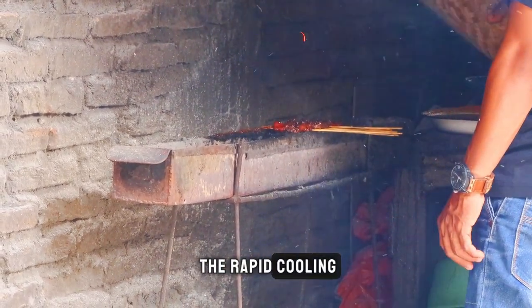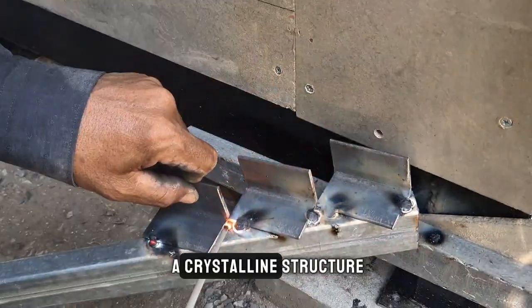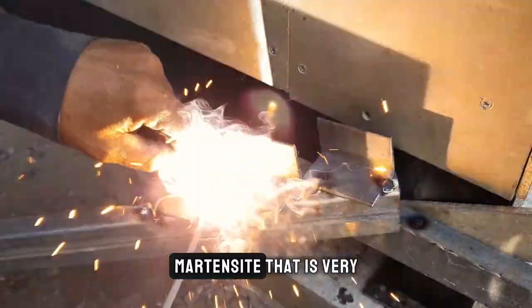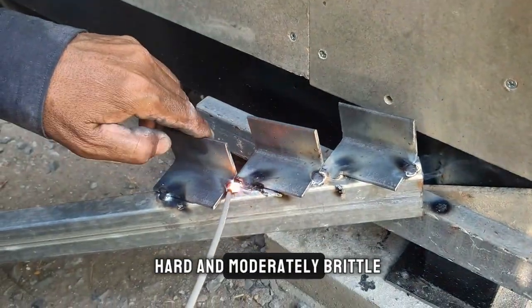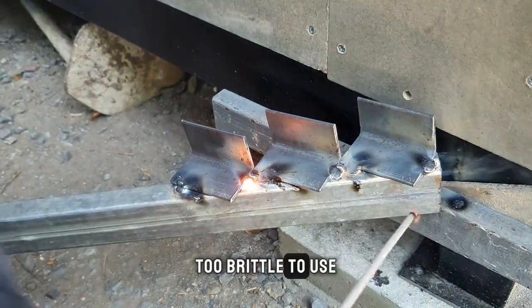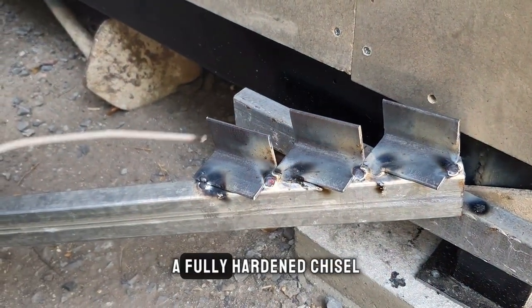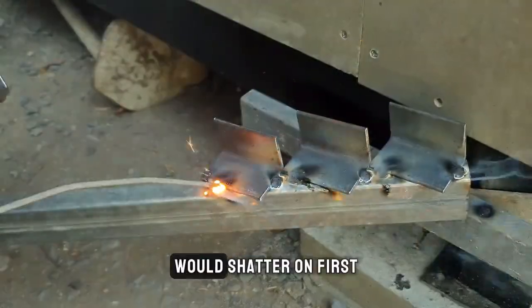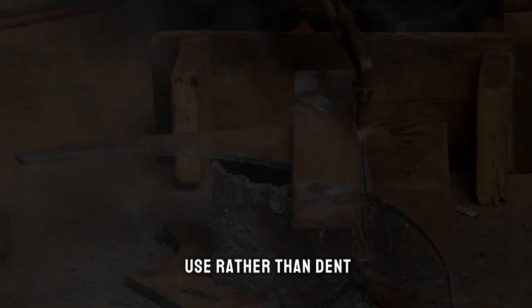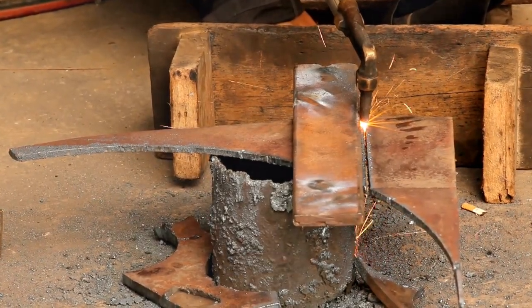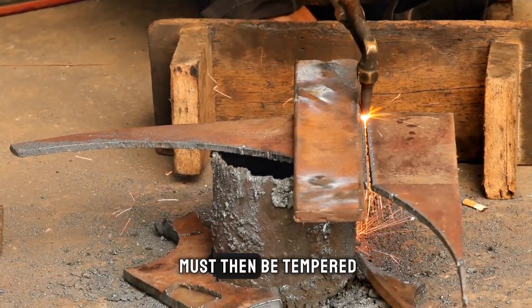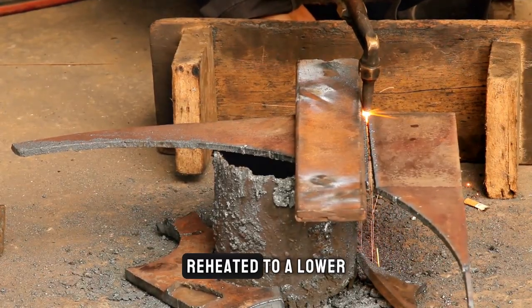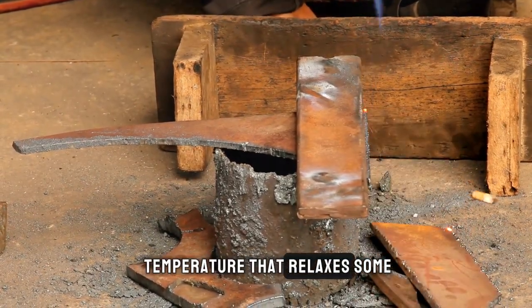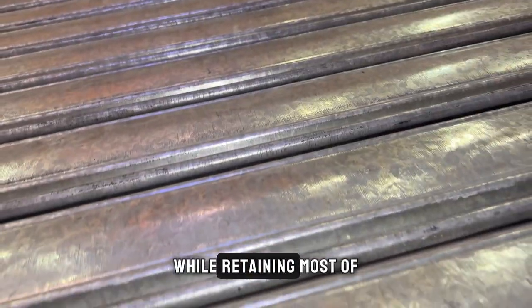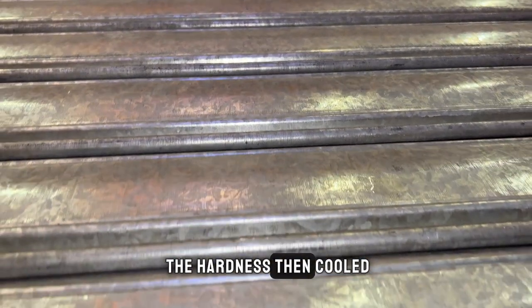The rapid cooling locks the carbon in a crystalline structure, martensite, that is very hard and moderately brittle, too brittle to use as a tool. A fully hardened chisel or hammer would shatter on first use rather than dent or deform. So the hardened tool must then be tempered, reheated to a lower temperature that relaxes some of the brittleness while retaining most of the hardness, then cooled again.